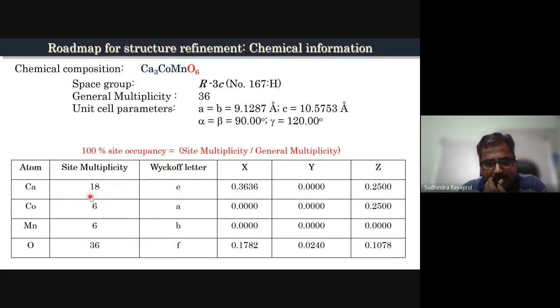Okay. So thank you. So now, the calcium. In my composition, I have calcium, cobalt, manganese, and oxygen. So my calcium I can put at the 18e site. So the general position is x,0,z. X I have to either determine from the crystal database, or I can refine the starting value and get to these values. Similarly, cobalt I can place at the 6a position, which is 0,0,1/4.